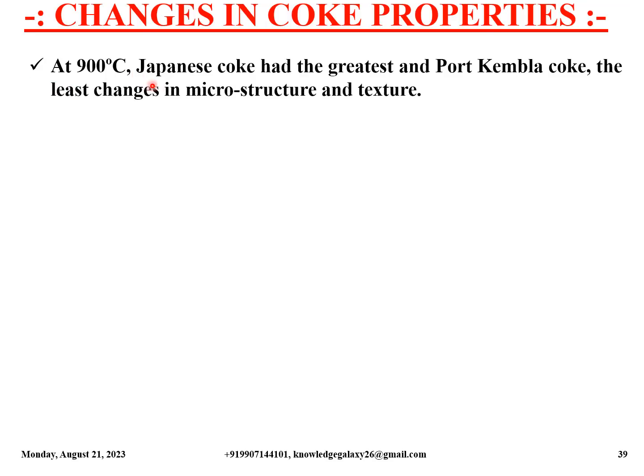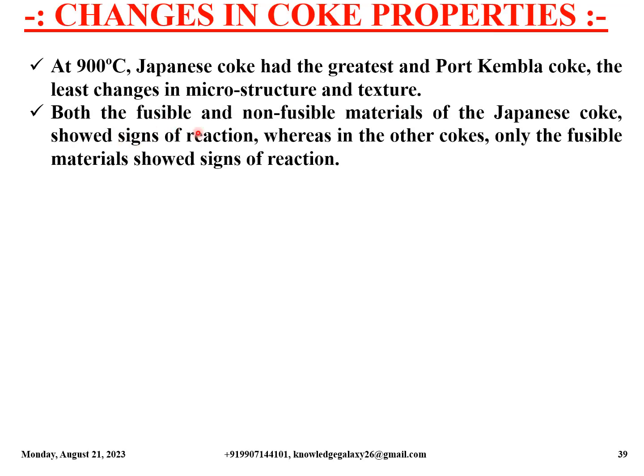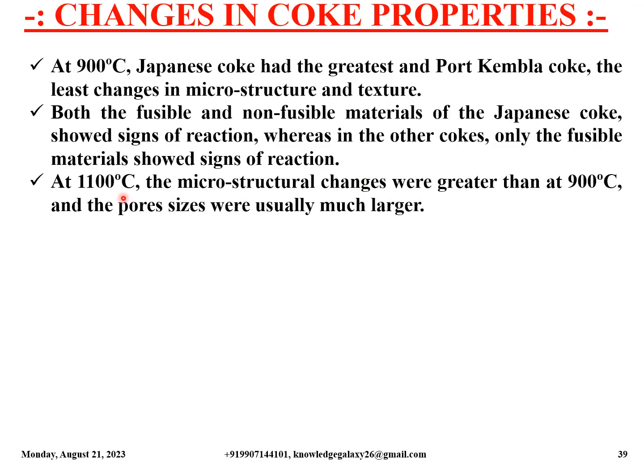At 900 degrees Celsius, Japanese coke had the greatest and Port Kembla coke the least changes in microstructure and texture. Both the fusible and non-fusible materials of the Japanese coke showed signs of reaction, whereas in the other cokes only the fusible materials showed signs of reaction. At 1100 degrees Celsius, the microstructural changes were greater than at 900 degrees Celsius, and the pore sizes were usually much larger.